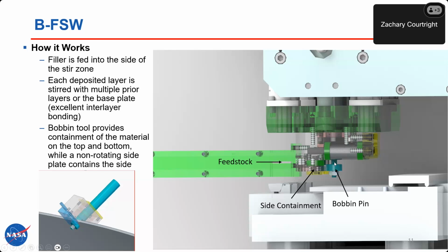And then what's not shown in this image would be a plate that would be clamped in place, where Joseph's pointer is there, or where he showed in that image on the bottom left. It could be part of a dome or something like that. So basically the tool rides along, and right now we proved about 7/8 of the tool is engaging into the plate or the prior layers, and then 1/8 of it is not engaging, but it's where the filler material is coming in and being stirred in. So with every pass, it is stirring.